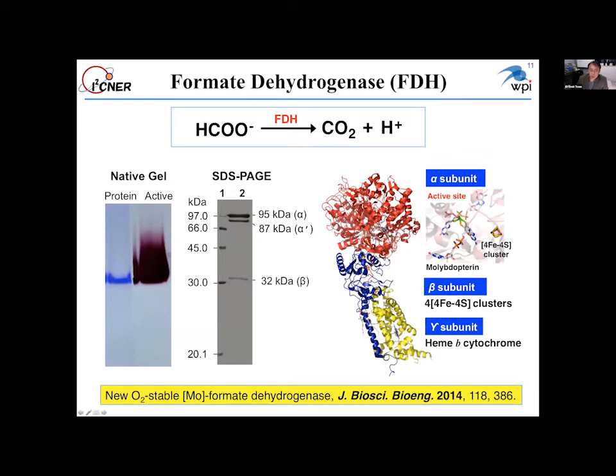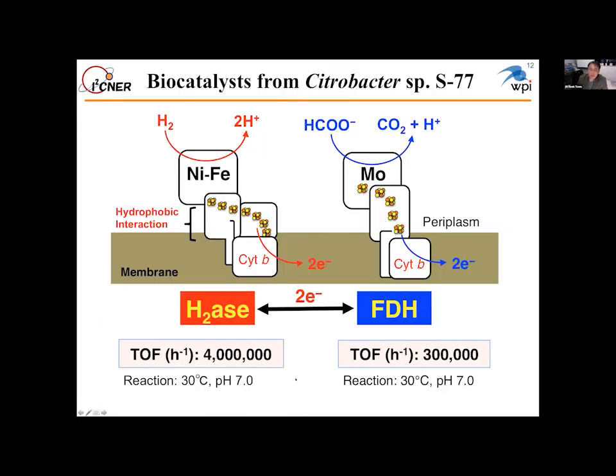This is very active. And what's interesting is that the active site contains molybdenum. We also published this. And I think if we use this enzyme and combine these two systems, the hydrogen energy electrons may be used for reduction. Usually formate dehydrogenase is used only for formate oxidation, but if we conjugate them, maybe we can use the electrons for CO2 reduction.